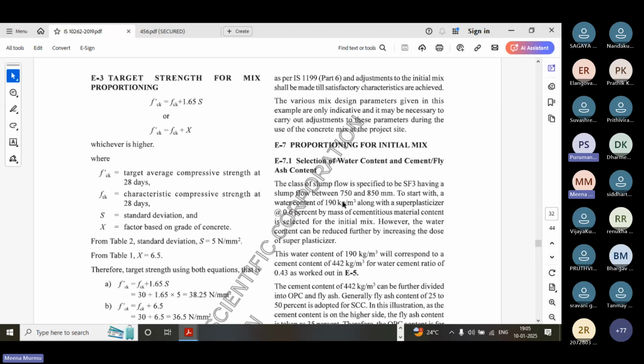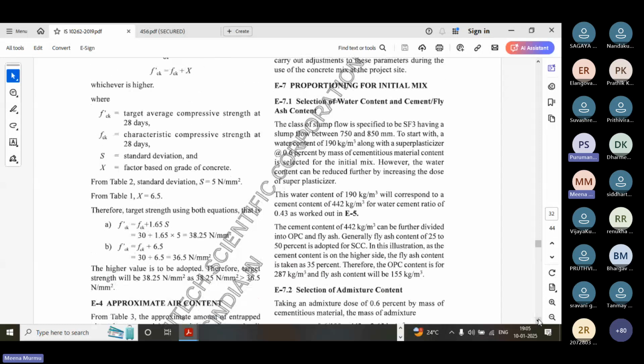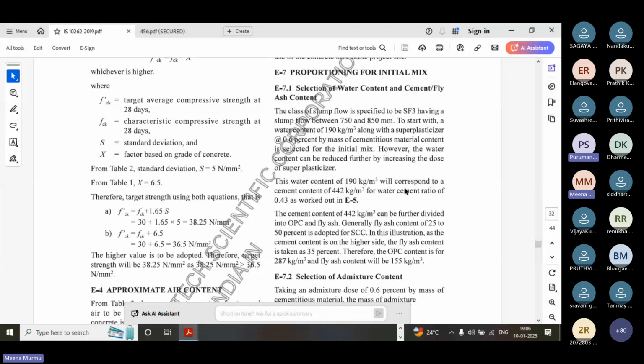So we are taking slump flow 3, which is the higher one. So water will start from 190 kg. As per the coarse aggregate, we normally assume the water quantity by workability, but here we directly start as per the slump flow value, whether it is lower, higher or medium. So for that we have started with 190 kg per meter cube of water, and the water cement ratio is 0.43. Corresponding to this, the water content is 190 kg, and the cement content is 442 kg.